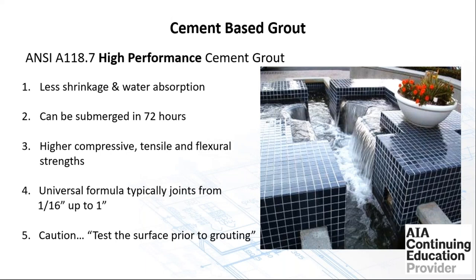Advantages: less shrinkage and water absorption, can be submerged in 72 hours, higher compressive, tensile and flexural strength, universal formula. So you can have one grout on the job site. You don't need to get a sanded or unsanded, 1/16 up to 1 inch. So one product on the job site will handle all the grout for that project. Makes it very easy, very universal.